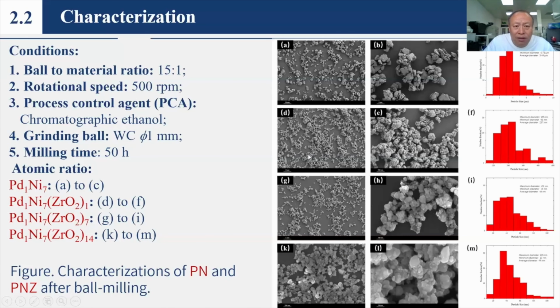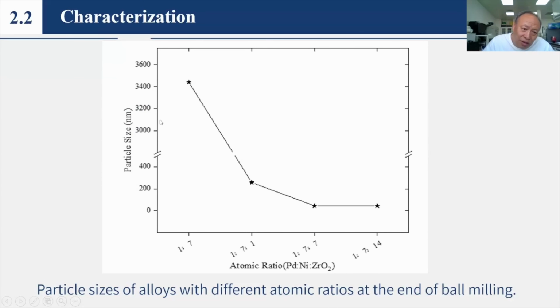And these are pictures of different compositions of zirconia. The first row is Pd1 Ni7, the second row is Pd1 Ni7 Zr1, and the last row is Zr14. We can find the grain size decreases with the increase of zirconia. And this is the particle size, from 3,400 nanometers for PN samples to only about 30 or 50 nanometers for PNZ samples.